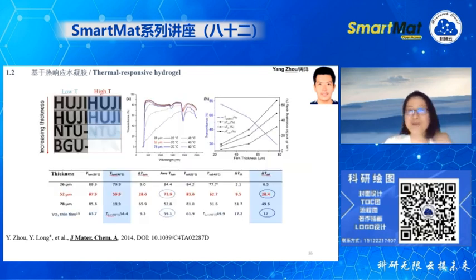Okay, so this is the very first paper. You can see it's actually very simple. We can just laminate hydrogel between two glasses, and very quickly we can see, compared with vanadium dioxide, we can get delta T-SO of 20 compared with VO2 only 12, and the average T-lum is 73, compared to VO2 only 60. So by simply applying a very thin layer of hydrogel between the glasses, we can quickly enhance both T-lum and delta T-SO at the same time.